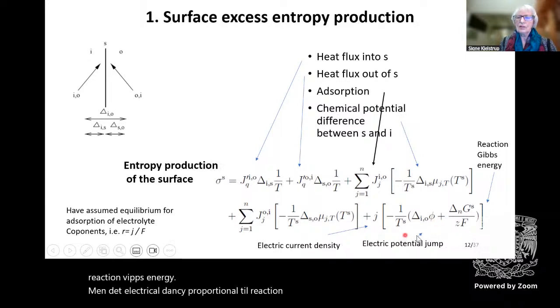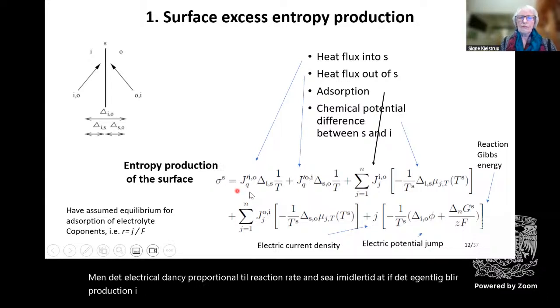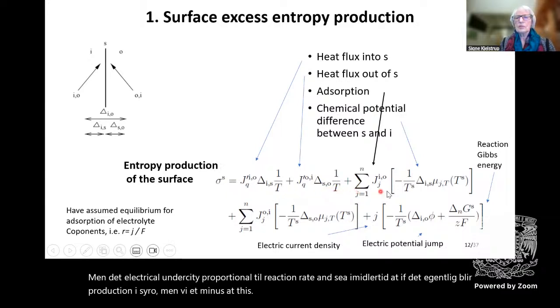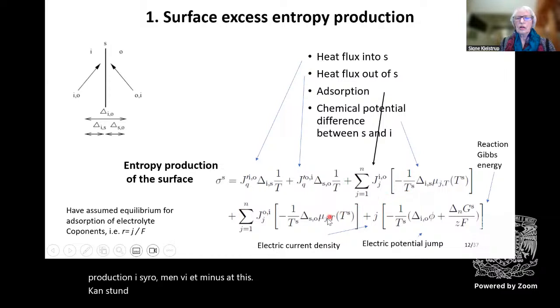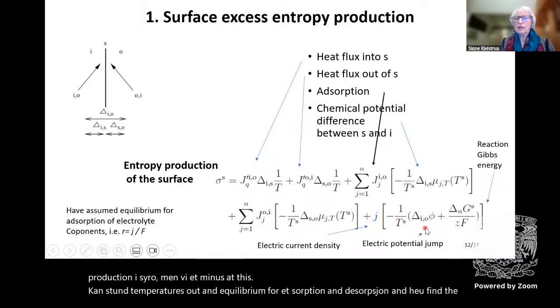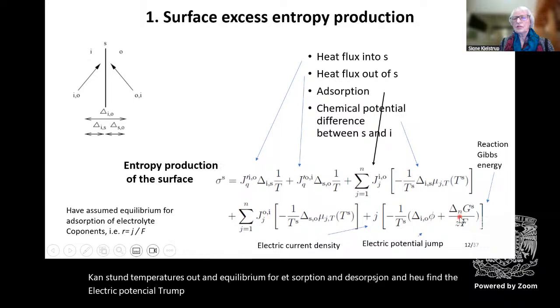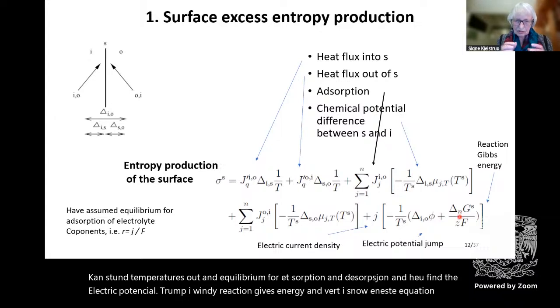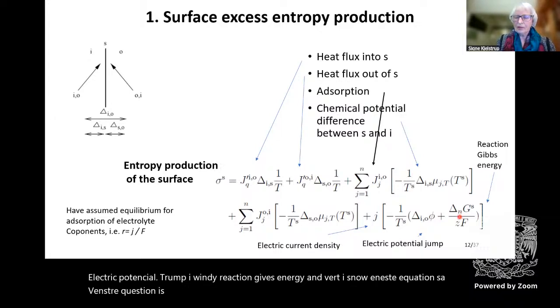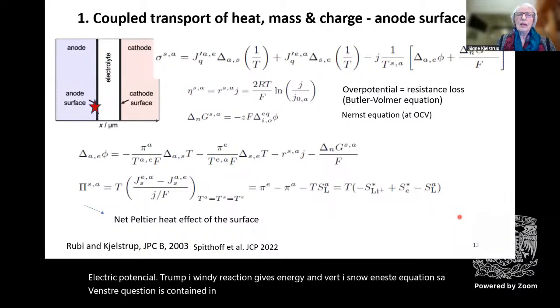And you see immediately that if the entropy production is zero, it means that there is constant temperature throughout and equilibrium for adsorption and desorption. And here you find the electric potential jump given by the reaction Gibbs energy, and that is now the Nernst equation. So the Nernst equation is contained in this formula. And I'm going to use a simplified version.